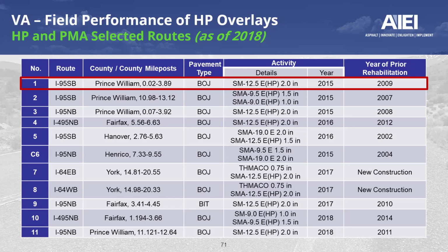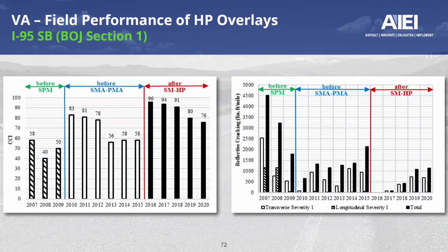Taking you through a brief example for the sake of time, on I-95 southbound in Prince William, you will see that it was a 2-inch dense graded surface mix. It was a 12.5 mm mix constructed on top of a jointed concrete pavement. That was constructed in 2015, and the prior rehabilitation was in 2009. Through the pavement management system, VDOT employs what we call the Critical Condition Index, with 100 referring to excellent pavement performance and 0 to totally failed performance, with a cutoff limit of 60.